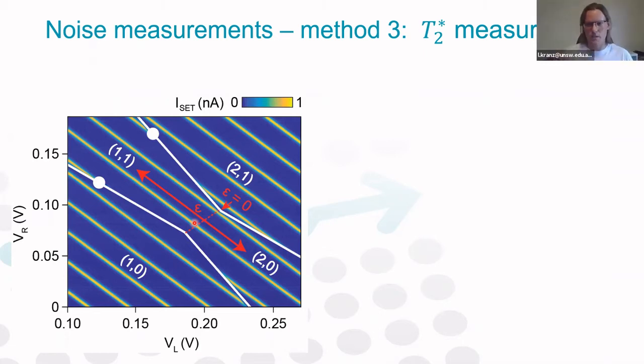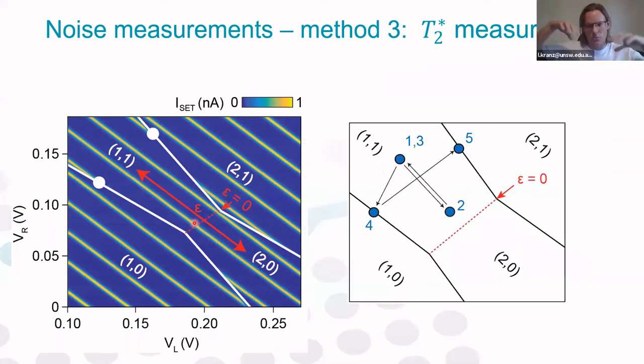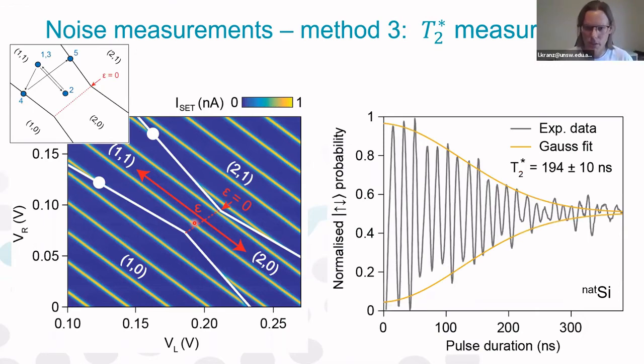What we do in the experiment is start in the 1-1 region with separated electron wave functions. We then perform this detuning pulse to overlap the two wave functions, and we time that, and then we separate the wave functions again, and we perform independent spin readout on both qubits. With this pulse sequence, we get this data. What I'm plotting here is the probability of measuring the up-down state as a function of the duration spent at this point 2 over here. And we see that this probability oscillates, and these are called exchange oscillations or coherent swap oscillations.